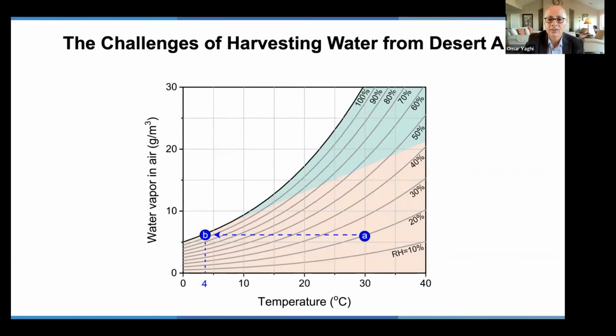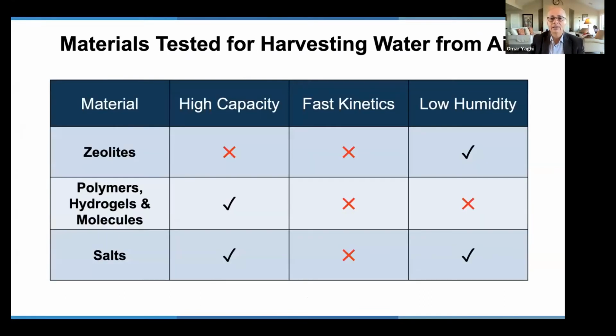Now, if I have a MOF that is designed to extract water from air here, then I would concentrate the water into the pores of the MOF and therefore create a more humidified environment. And therefore, to get the water out, I would only need to reduce the temperature to 4 degrees in this example. So this blue line is not a viable method of extracting water from air. The red lines show you that you can turn desert air into tropical air by harvesting the water into a porous material. Again, there are many materials being investigated for water harvesting. And if they don't meet one of these criteria, having high capacity, having fast kinetics, or working at low humidity, they are not going to address the water stress in the way I have been describing.